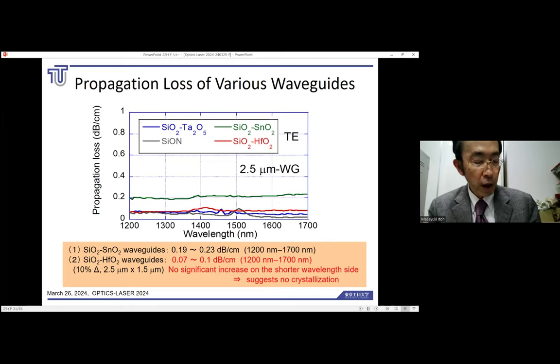The silicon dioxide, tin dioxide waveguide has a propagation loss of 0.19 to 0.23 dB per centimeter in the 1200 nanometer to 1700 nanometer wavelength band, which is much higher than that of other waveguides. The silicon dioxide, hafnium dioxide waveguide has a propagation loss of 0.07 to 0.1 dB per centimeter in the 1200 nanometer to 1700 nanometer wavelength band, which is similar to that of other waveguides, indicating a low loss waveguide.